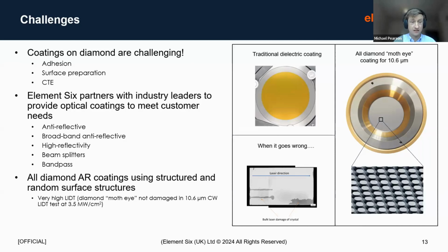And the benefit of this system is that your LIDT is much higher than for traditional dielectric coatings. So if you can take a small hit on spectral performance on your transmission, then you can achieve much higher LIDT threshold using either a structured or a random surface structure AR coating.